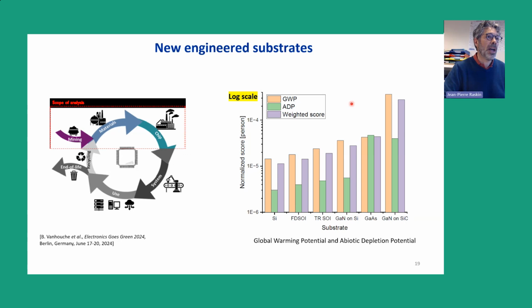Now you can use, of course, LCA, life cycle assessment, to think about the use of the starting materials of your process. It means the substrate. And there are a lot of different works on substrate engineering to use the correct substrate for the correct application. For example, here we have made a study in my group studying different types of substrate for high frequency and high power applications. Be careful here with the scale you see for those two indicators, which are the global warming potential, basically the CO2 equivalent emission, and the abiotic depletion potential. And we see that for the same performance, it's very important to try to move to silicon-based substrate, even if you can use on top of those silicon substrates III-V materials to take advantage of those wide band gap semiconductors or high mobility semiconductors.